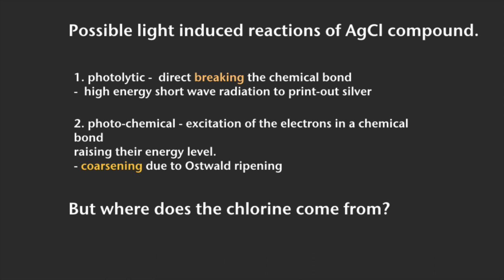So causing a coarsening. So what I think the mechanism here is basically Ostwald ripening, and it's natural for very small particles with large surface area to want to join together to form larger particles with a smaller surface area. Emulsion technologists use this when they create halogens to increase their film speed. By allowing the gelatin to be liquid longer, you allow for more ripening to occur before you set the gelatin, so you create a larger silver chloride, silver bromide, silver iodide halogen and get a faster working film. If we think of the ripening, it also explains what I've observed as a daguerreotypist. When I sensitize a plate, it gains photographic speed if I wait.